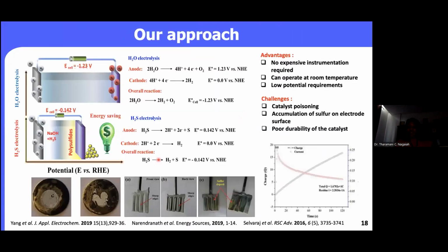However, when you have the H2S or the sulfur in the chemistry, the electrochemistry is not that simple. As you can see here, on the anode, we are producing the sulfur, and at the cathode, hydrogen, and the potential requirement is only 0.142 V. So the advantage is, again similar to the electrochemical, we don't need any expensive setup, and everything can be done at room temperature. The only challenge is the catalyst poisoning, and especially for the electrochemist, the accumulation of sulfur on the electrode. Once it accumulates on the electrode surface, obviously any activity decays because it acts as an insulator. And also the poor durability of the catalyst is one of the challenging tasks.